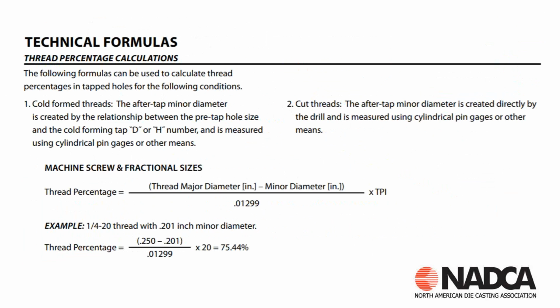But the problem with a form thread is you have to follow the draft of the hole. So at the top of the hole, you're going to have less percentage of thread than you will at the bottom of the hole. So if we have less percentage of thread and we form those threads and we have porosity inside that hole, porosity that was at the surface, shrink or gas, it's going to affect that thread integrity. So, going back to the original question, what is the standard?